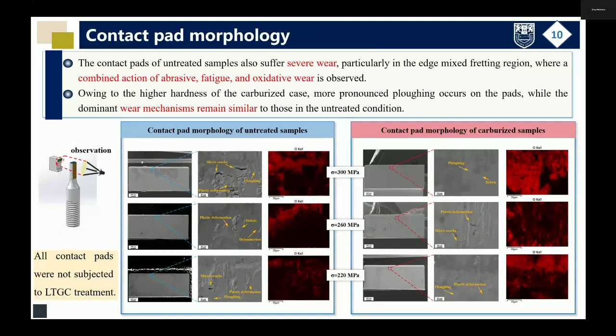The morphology of the contact pad is shown here. It should be noted that all contact pads were kept in the untreated condition and were not subjected to LTGC. The contact pad of the untreated sample also suffers severe wear, particularly in the edge mixed fretting region, where a combined action of abrasive, fatigue, and oxidative wear is observed. Owing to the higher hardness of the carburized case, more pronounced ploughing occurs on the pad, where the dominant wear mechanism remains similar to that in the untreated condition.